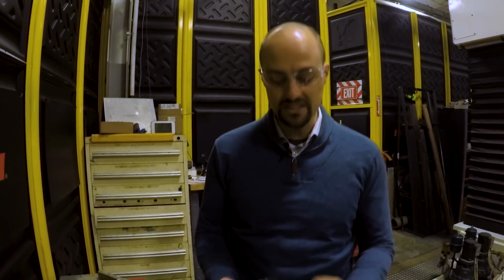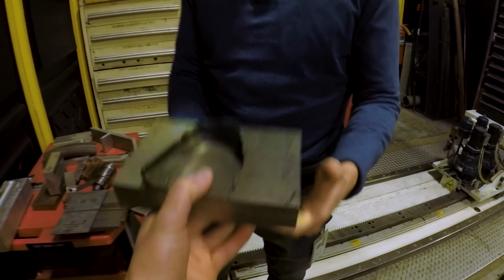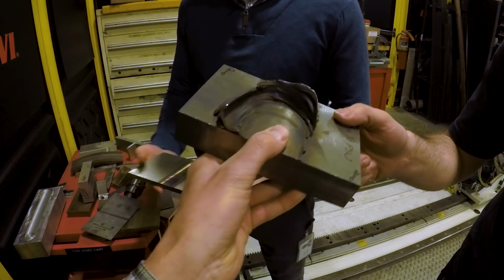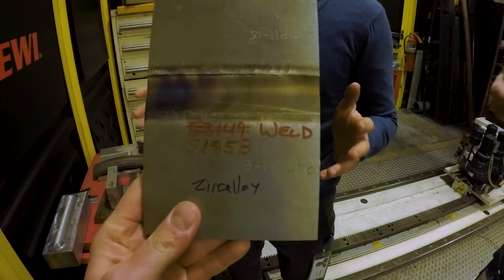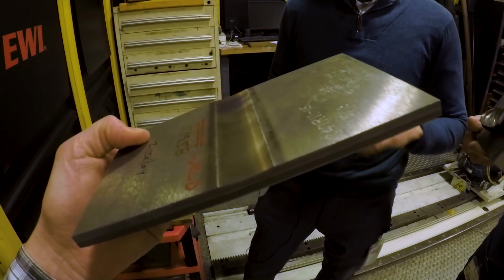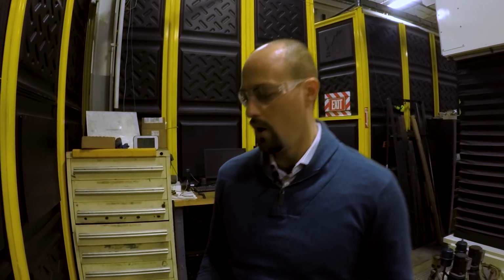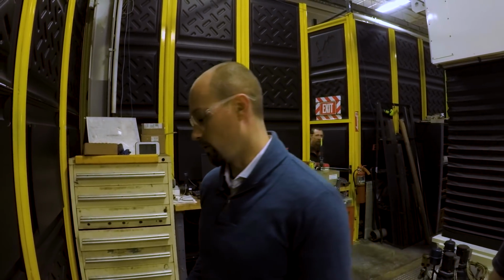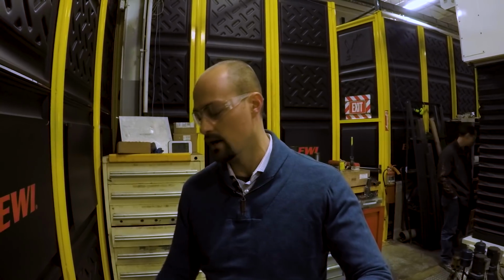It's funny. So, this is a 1-inch thick titanium weld, Ti64. And this is zircaloy. So, we have run the gamut of materials here, up to 1-inch thick in copper, up to 1 inch thick in steel. An inch of copper? Yes. The copper is great because friction stir welding leaves you with a very conductive microstructure. For things like bus bar applications, this is excellent because you can take something very close to commercially pure copper and join it and maybe only lose a couple percent in conductivity. And for things like land turbine generators, where heat generation is key because they're pumping so many amps through this, it's really an enabling technology to get away from brazing, where you have no quality control methods, and in the worst case, even a bad friction stir weld has a lot of structural integrity.